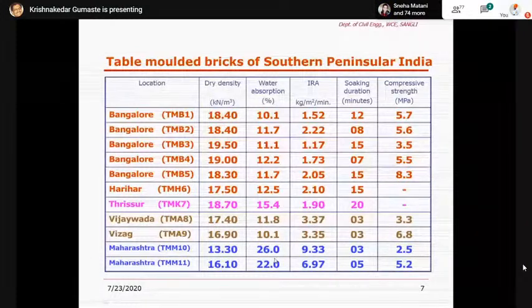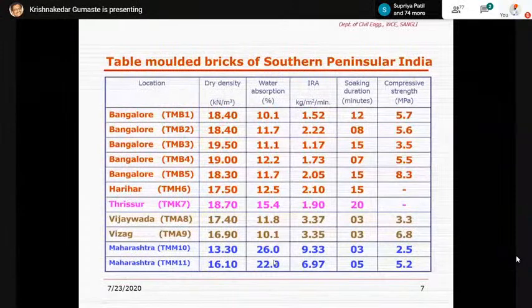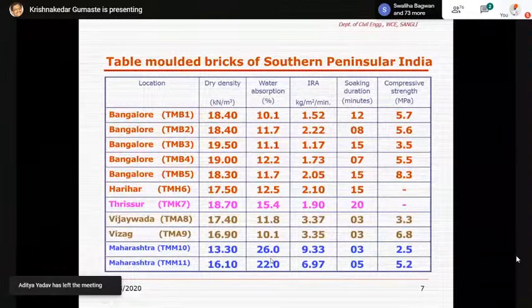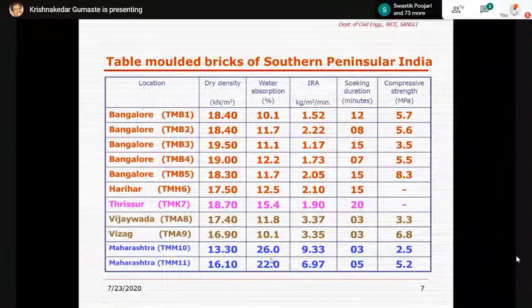But based on the criteria of Sangli and Pune, I cannot conclude that all the bricks in the state of Maharashtra are poor. So we further explored by bringing bricks from different districts of Maharashtra, and the results were observed to be the same: the bricks showed very high water absorption and low to moderate strengths, where none of the bricks crossed a compressive strength of about 5 or 6 megapascals in the majority of the districts.